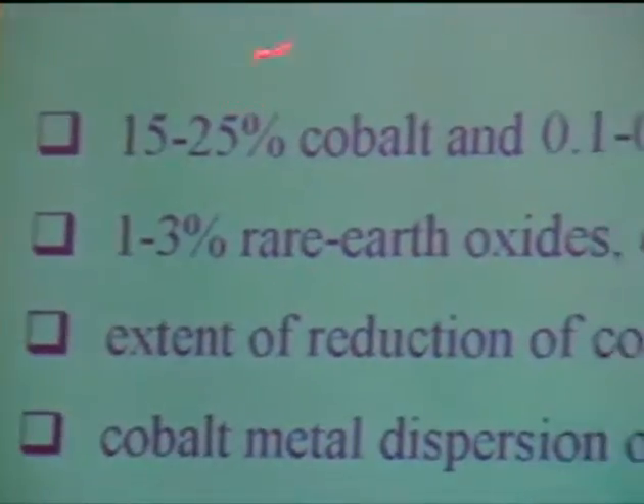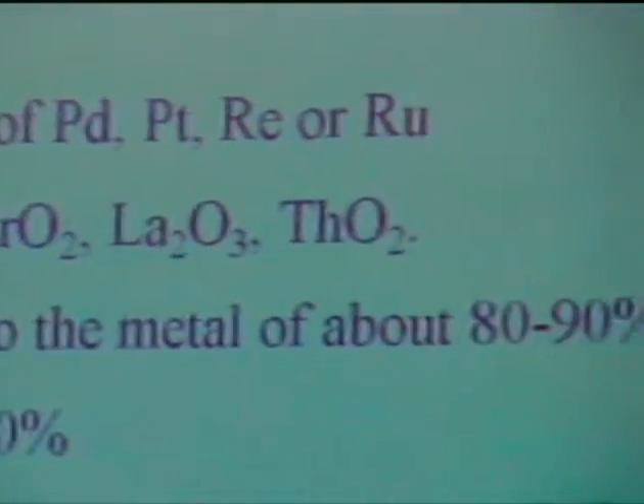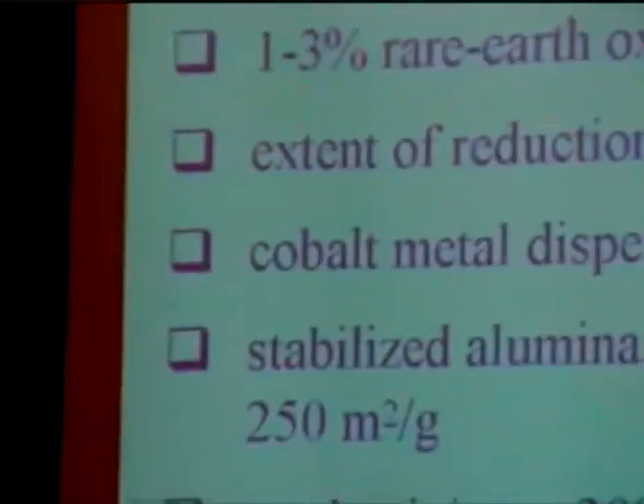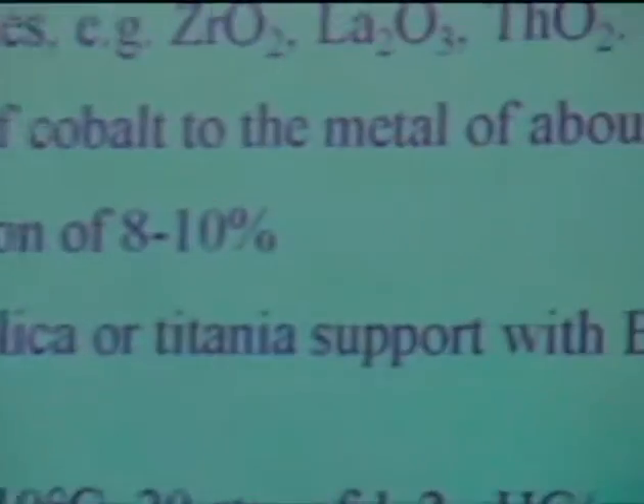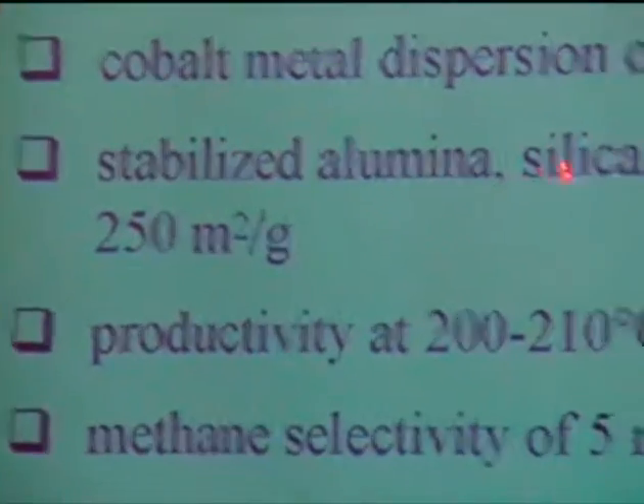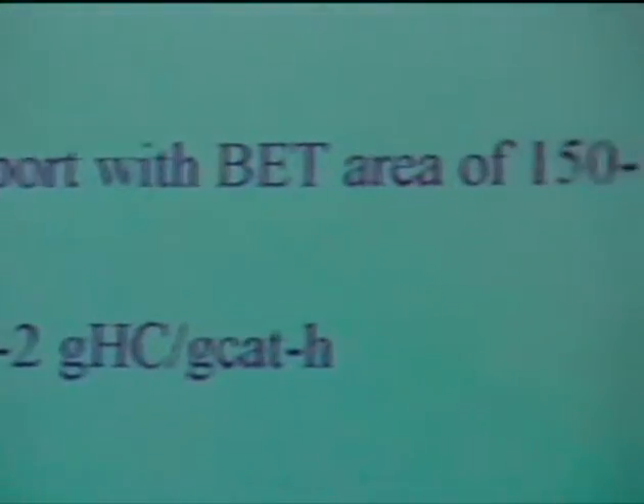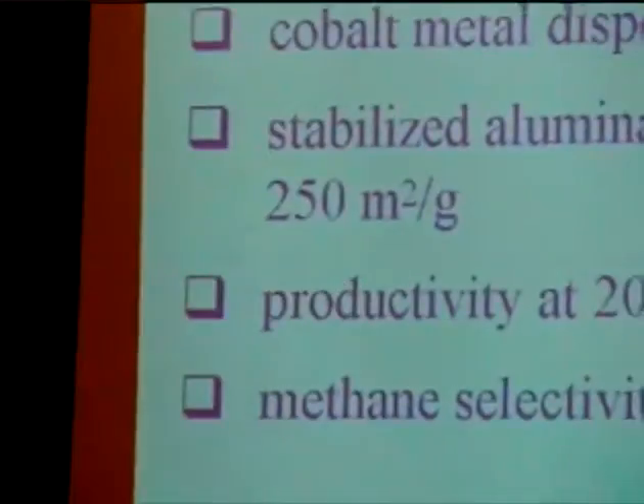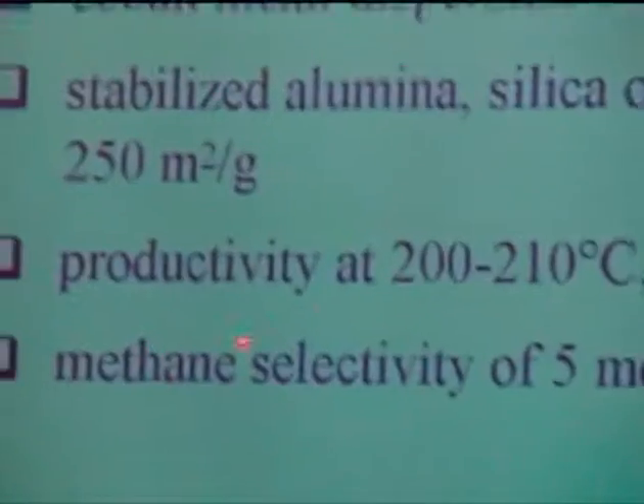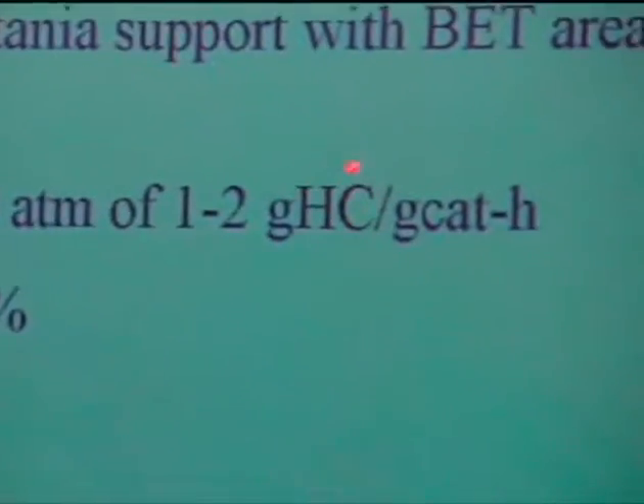Well, I won't go further, but all of this leads us to a state-of-the-art cobalt FT catalyst, which I propose involves about 15 to 25% cobalt, 0.1 to 0.5% precious metals, 1 to 3% rare earth oxide, extent of reduction of cobalt to the metal of about 80 to 90%, a dispersion around 8 to 10%, and a stabilized alumina, silica, or titania support—preferably alumina—with a BET surface area of 150 to 250 square meters per gram, a productivity of 1 to 2 grams of hydrocarbons per gram catalyst per hour, and a methane selectivity of around 5 mol%.